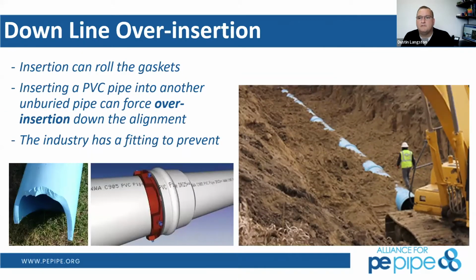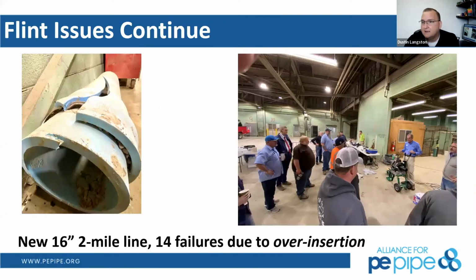Ford Meter Box has invented a fitting to bolt around the pipe to actually prevent and make sure that you do not over insert PVC. But if you're not, again, burying it or restraining it some way as you go, it can be susceptible to over insertion down the line. You're trying to stab that new stick in, and all of a sudden things get hung up, you're at too much of an angle, whatever the case, and it might have an easier way down line to move. So very, very important to make sure there's no over insertion. Flint actually had some issues like this with a 2-mile, 16-inch line, 14 failures due to over insertion.